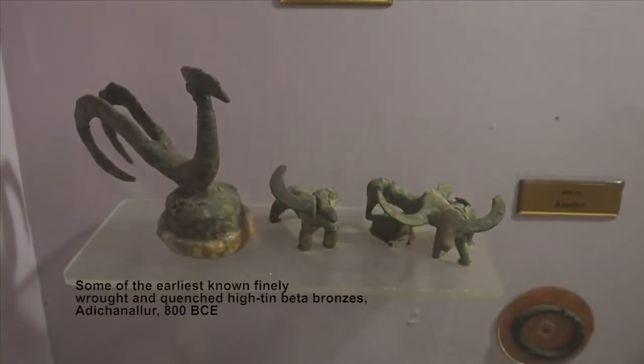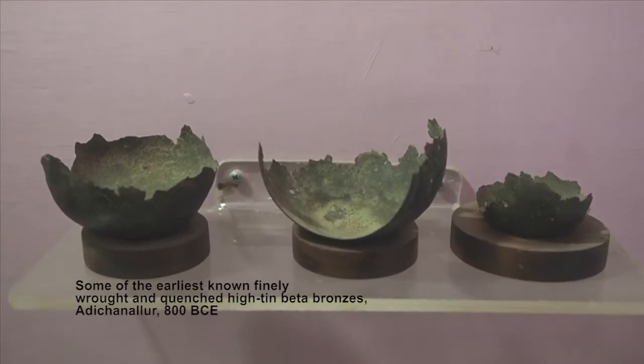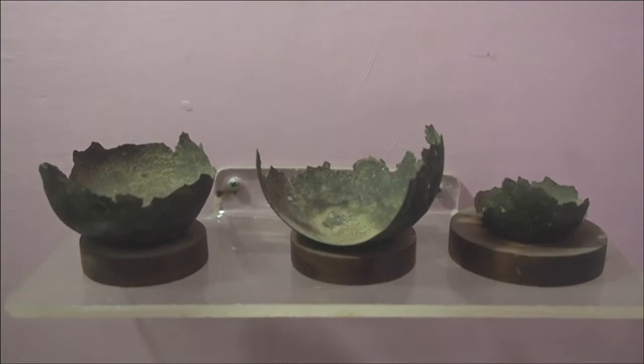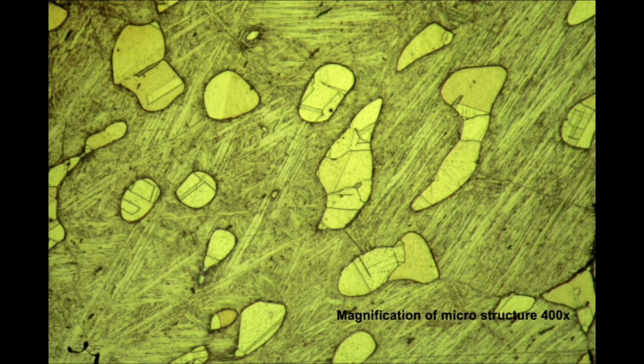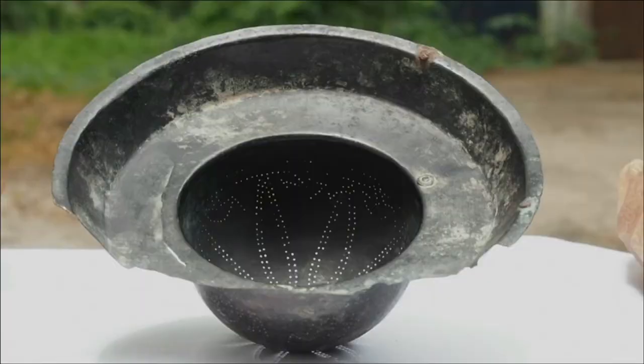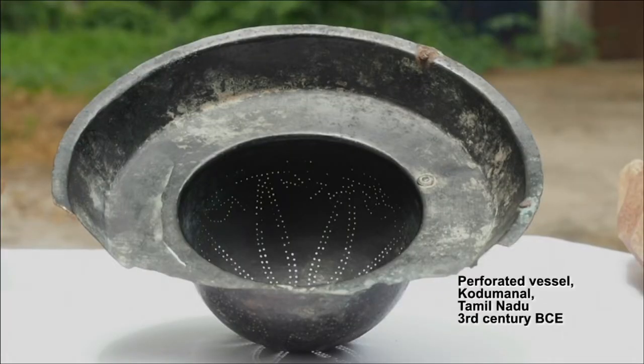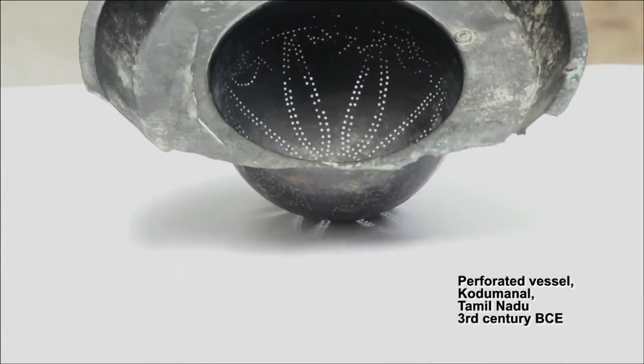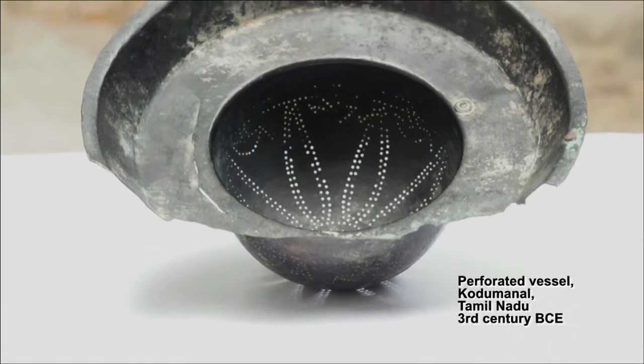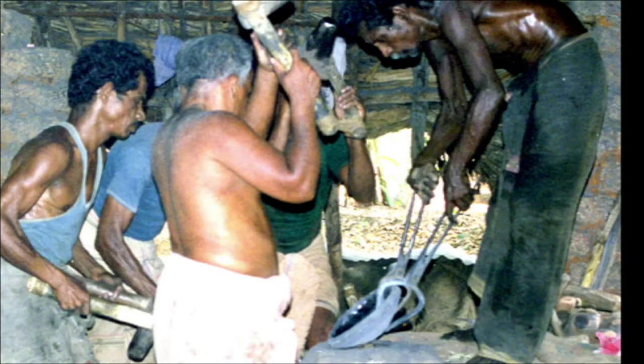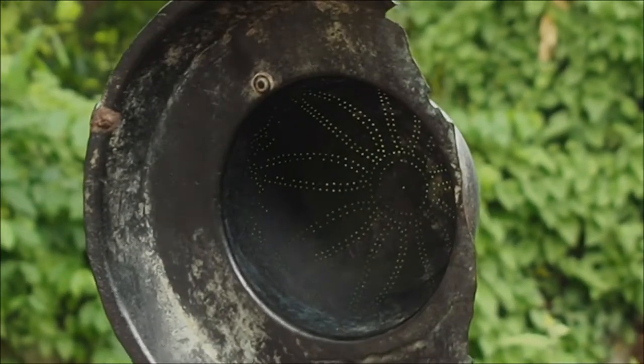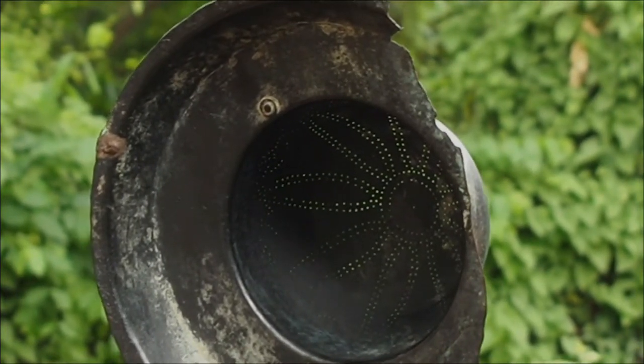Astonishingly, from the megaliths of Adichanallur, we find extraordinary examples of high-tin beta bronze. The microstructure of a wrought and quenched high-tin beta bronze vessel from Adichanallur shows that it has islands of alpha interspersed in an extensive matrix of beta phase, needle-like beta phase, which has been retained due to the quenching process. This is also seen from the megalith of Kodumanal excavated by the State Archaeology in Chennai, which yielded an extraordinarily thin perforated vessel. Bronze of a composition of about 23% tin has been extensively hot forged and then quenched to give vessels of an extraordinary thinness, down to less than a millimeter.